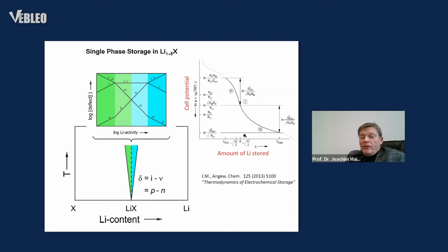So when you have the opinion, this is just equilibrium and has nothing to do with kinetics, it's not so, because usually the kinetics are determined by the solid-state diffusion that inside is pretty sluggish. And the chemical diffusion has to do with the conductivities of ions and electrons. And they also derive from this figure. So this figure is crucial in electrode research, but almost none in the battery field is looking at these.